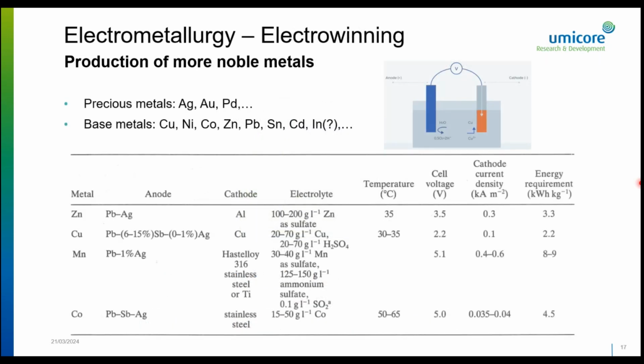Then we go to electrowinning. So this is what we are actually doing in Umicore. We are also performing electrowinning. So in electrowinning, you do it in aqueous media, usually in an acidic solution. You can see here, usually in a sulfuric acid solution. You have a cathode on which you deposit a metal such as copper. At the anode, you have oxygen. You oxidize water to oxygen. As you can see here, the temperatures are much lower.